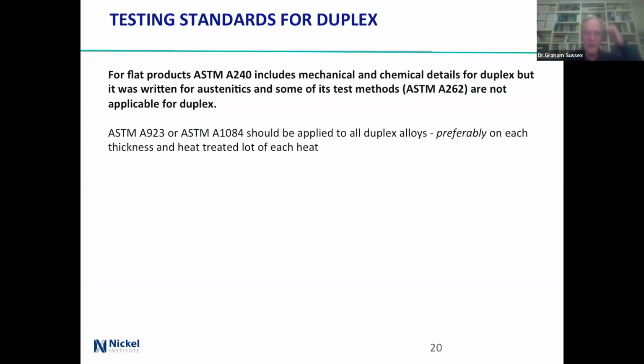Okay, testing standards for duplex. For flat products coming to ASTM A240, and I'm sorry, I do tend to run to the American standards, mechanical and chemicals, but some of the tests were written for austenitics, and some of them, A262, for instance, just don't work. 923 and 1084 work for duplexes, although 1084 typically is used for the low and lean, and 923 for the ones that get king hit.